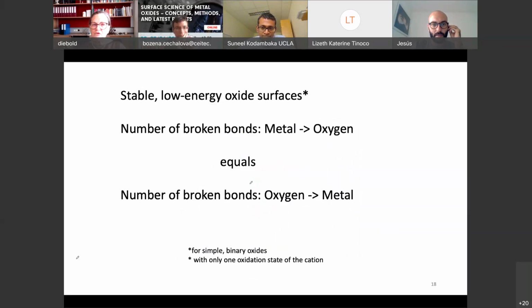When we want to create stable low energy surfaces, so if you cut the material in half in one specific crystallographic direction, then in order for these surfaces to have low energy, which means A, they're stable, and B, they're very common in nature, those are the ones we really should look at. There's a very simple rule for these simple binary oxides that I talk about, TiO2, indium oxide, and so forth, with only 1 oxidation state of the cation. There are caveats, but the rule is really simple. The number of broken bonds metal to oxygen should equal the number of broken bonds from oxygen to metal.